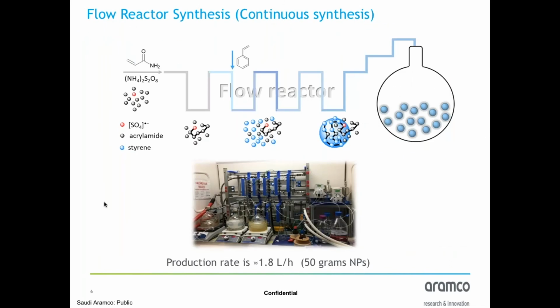I'm trying to move to the next slide. Yes. So this is an illustration of our developed hybrid process combining flow mixing with batch polymerization, the flow-to-batch method, to produce the nanotags at a rate of 1.8 liters per hour in the lab. The synthesis of the nanoparticles via low surfactant loading or surfactant-free emulsion polymerization is very simple, scalable, and cheap, both in a small batch as well as in the large scale state-of-the-art flow reactor.